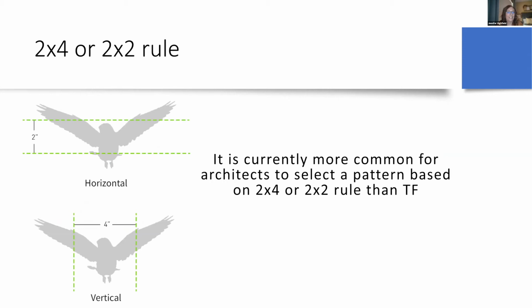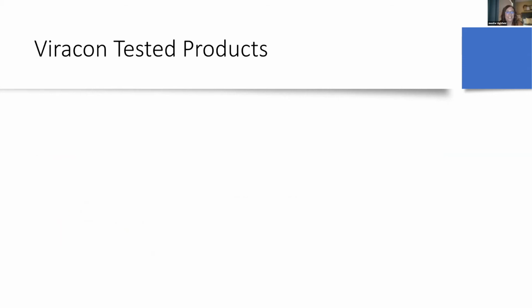Oh, actually go back one. Perfect. Looks like this is not showing the patterns. We have 3 more additional patterns and colors that were tested with ABC. This includes 2 line patterns that are digitally printed with alternating white and translucent frit. The glass with the best performance was the dark gray, 1/8-inch lines alternating with 1/2-inch spaces. In the test, this pattern and color combination deterred 94% of the birds, which equates to the threat factor 6.